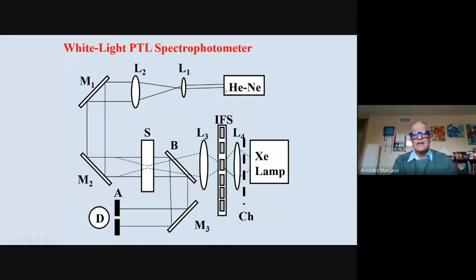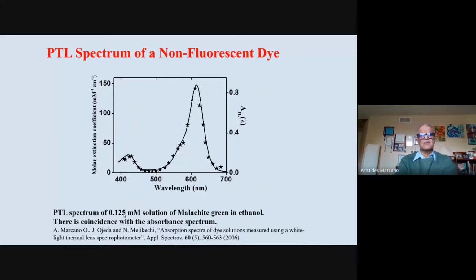Then we send the HeNe laser, the red light, the probe beam, collimated into the sample, and we observe what is happening right here. So we are able to do this even with the lamp. I'm just observing some samples there. Here, for example, we have a sample which is malachite green in ethanol. Malachite green is a non-fluorescent dye. There is no fluorescence, and you can see a very good, excellent agreement between thermal lensing and absorbance. So there is nothing else but heating being generated in this case.